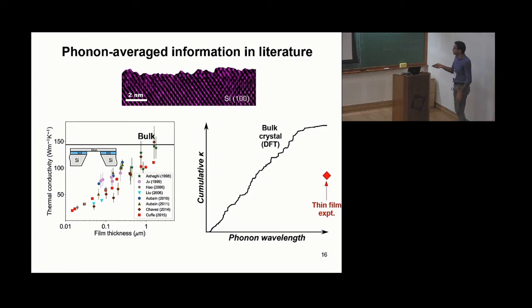To give you a more detailed explanation, I'm showing the thermal conductivity accumulation as a function of phonon wavelength. Wavelength is another property with which you can tag the phonons, and these experimental points are the total accumulated value, so these points will lie somewhere at the right end of the spectrum.